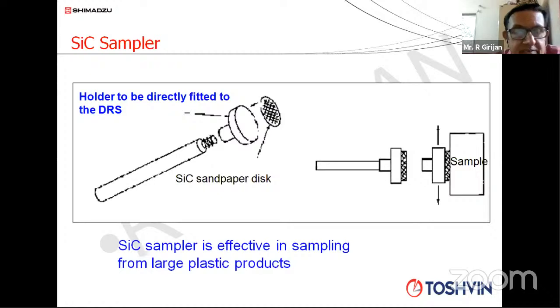You can use this accessory. You can go and just rub it on the surface of the tank a few times. There is an abrasive material, which is shown as a black disc here. That's a sandpaper disc, called abrasive. It's a silicon carbide material. So when you are rubbing it, because it is an abrasive material, a few particles of the polymer tank will stick to this. Come back to the lab, keep this abrasive disc on the DRS attachment, and you can record the